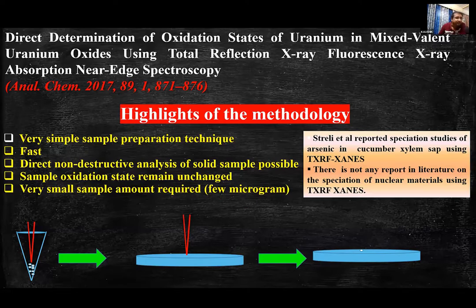On the other hand, the sample oxidation state remains unchanged. As we are doing minimum sample preparation, there is no chance that the sample could get oxidized. And as a very small amount of sample is required, roughly a few microgram to a few nanogram, this methodology is very important for speciation studies of highly radioactive materials.